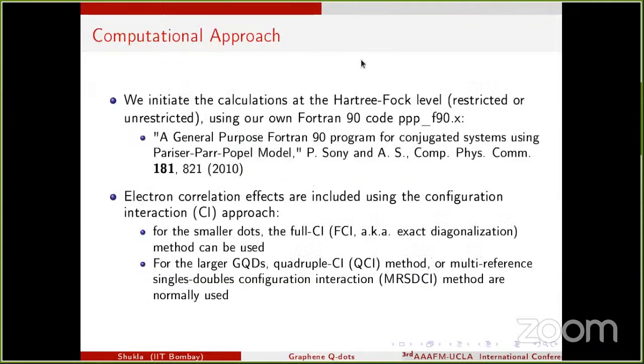Let me briefly give our computational approach, because this is different from most of the DFT calculations and other first principles calculations. We initiate the calculations at the Hartree-Fock level using the PPP Hamiltonian. For the purpose, we use our own program, which we published in 2010, and it's publicly available if anyone is interested. Then after obtaining the molecular orbitals, we transform the Hamiltonian from site representation to molecular orbital representation, and include the electron correlation effects by means of configuration interaction approach.